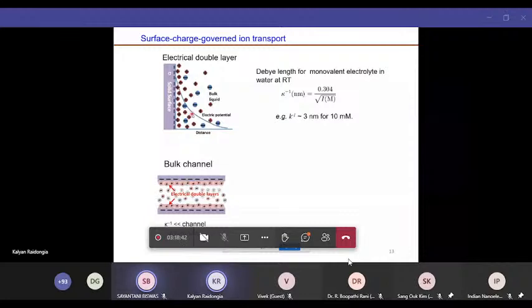But nowadays, we can make a large number of channels of very small size. For example, when these two surfaces come very close to each other, the Debye lengths overlap. Once the Debye length overlaps, no matter what is in the solution outside, in that overlapping region we will have ions only of charge opposite to that of the surface. If the surface is negatively charged and the channel is very small, the whole channel will be occupied by cations. And this concentration of cations depends upon the number of charges on the surface. So this is a region called the surface charge governed region.